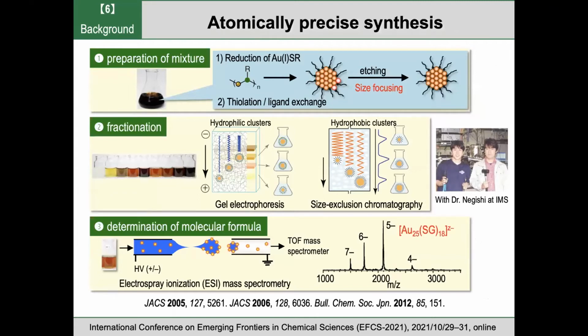And the method is composed of 3 steps. The first step is the reduction of metal ions in the presence of thiol. And after some etching treatment, we have a mixture of stable clusters in solution. The next step is the fractionation of these mixtures by size using this separation technique. Then after this separation, we have a series of clusters like this from a brownish mixture.